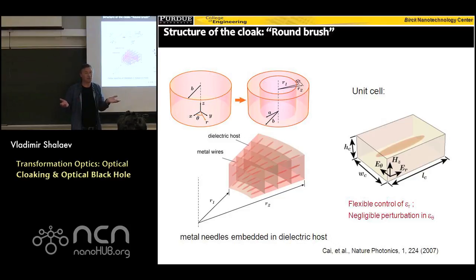It's just a question of putting the right amount of metal there. Metal has epsilon negative and large, like minus 5 or whatever. By choosing the right filling factor, you could make the effective epsilon 0, because you mix something positive, plus 2, and negative, let's say minus 10. It could be minus 10 or minus 100, depending on the wavelength. It means that you should not put too much metal, because epsilon is really large in magnitude. And so the effective permittivity would be zero. But since the metal filling factor decreases outward, you could make the effective permittivity go from zero to one,